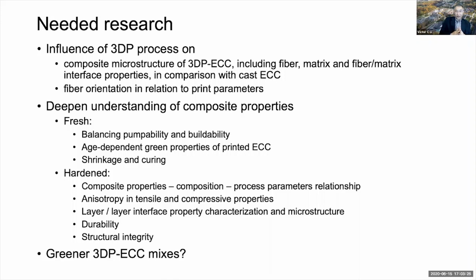There is definitely a need for deeper understanding of the influence of the 3D printing process on the composite microstructure in the fiber matrix interface, and how that differs from the regular casting process. The orientation of the fiber clearly is important in controlling the mechanical properties, as well as the anisotropic behavior of the printed layers, and therefore the structures. We need to deepen our understanding of the composite properties, both in the fresh state as well as in the hardened state. In the fresh state, the balancing of pumpability and buildability is always important for all 3D printing of concrete material, but definitely even more so in the 3D printing of ECC material.